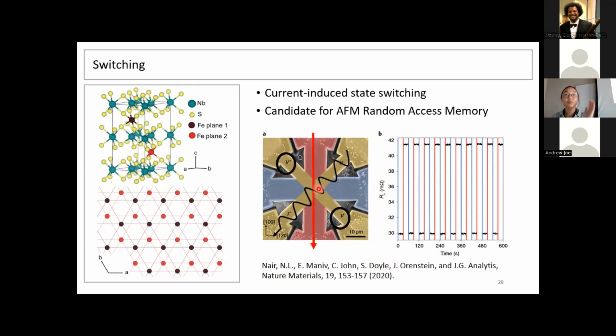We send a very brief current pulse in one direction, say this vertical direction. When that's done, we're in a high resistance state. We run a very brief current pulse in the horizontal direction. When that's done, we're in a low resistance state. So basically, we're sending these very short current pulses in order to change the resistance of our material.